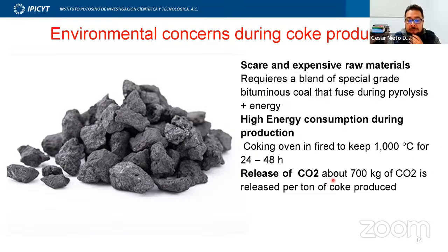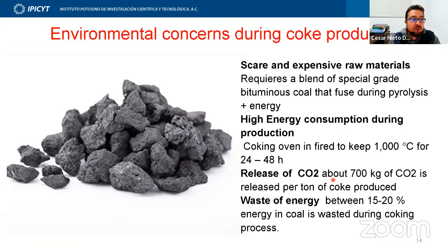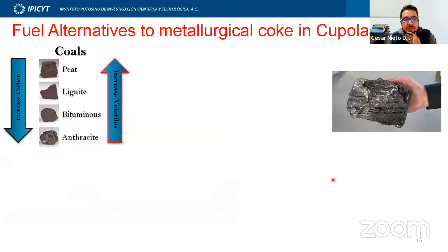Also, it releases a lot of CO2, and it's CO2 that is coming from fossil fuel, right? Here is just a very rough number. Around 700 kilograms of CO2 is released per ton of coke produced, which is a very large amount of CO2. And also, there is a lot of waste of energy. The bituminous carbon that is used as raw material to produce coke is essentially pyrolyzed during the production of coke, and between 15 and 20% of the energy that bituminous carbon has in it is just wasted. Well, anyway, there are some other drawbacks.